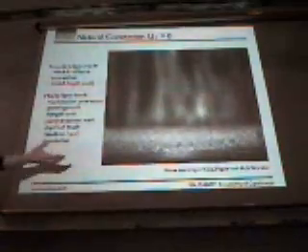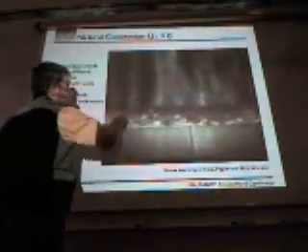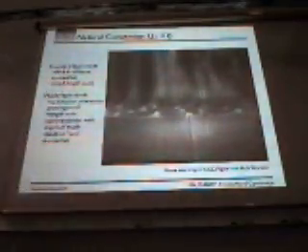So if I show a movie of this process, here's a tank in which we cooled from below. You initially get this mushy layer that forms, and you get a boundary layer mode of convection which rapidly goes to this mushy layer mode of convection, in which you get these thin plumes rising from this reactive porous medium.